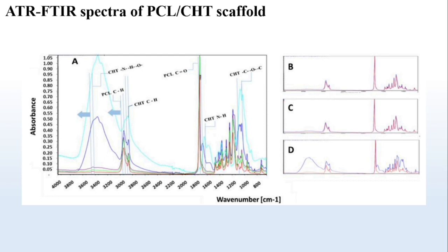The FTIR spectra of the membrane bottom surface show characteristics matching past reported values. In crude chitosan, reported peaks at 3364 indicate intramolecular hydrogen bonding between nitrogen and hydrogen and between oxygen and hydrogen, with the peaks at 1420 for asymmetric bending of a CH group. The PCL exhibits peaks at 2946 and 1726, representing the CH and ester carbonyl group respectively.